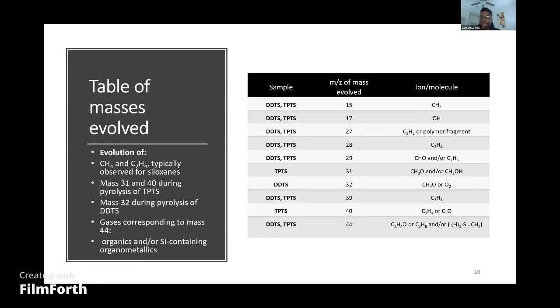In both these cases, during the pyrolysis of DDTS and TPTS polymer precursors, we do see the evolution of gases corresponding to mass 44, which can be attributed to the evolution of either organics or even organometallics that contain silicons, such as silenes. By that I mean silicons double bonded to carbons.